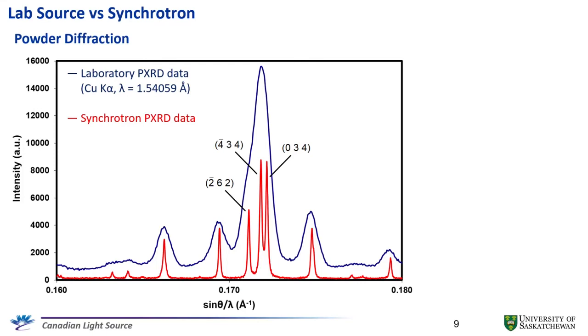Because a synchrotron has a very collimated beam. Basically, if you do diffraction, the parallel beam is masked, right? If you have a very parallel beam and a single wavelength, almost like a line, then you can get a very sharp diffraction peak. So with a synchrotron, you can differentiate some very close-by peaks so that they don't overlap, and you can detect the structures very accurately.